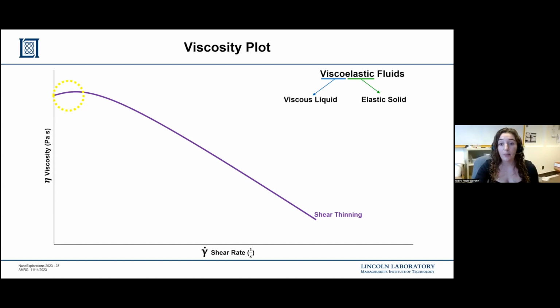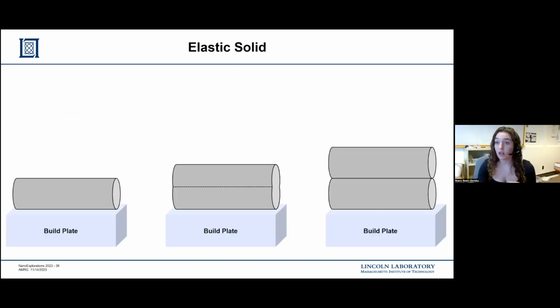And this is an important property because as we put our filaments onto the plate, we need that viscous liquid region to flow the ink out. But then once it's on the build plate, we want it to be an elastic solid. So when we apply the second filament on top of the first, it has this temporary moment of elastic deformation where the top filament sinks into the first. However, the deformation is only temporary. That's elastic deformation. And the bottommost filament returns to its original shape. This prevents the structure from collapsing in on itself. This is your self-supporting structure.